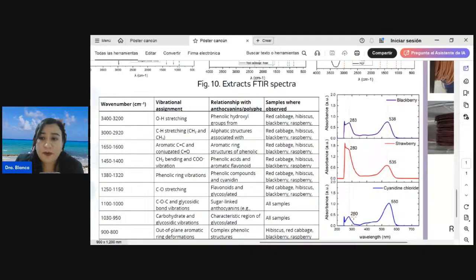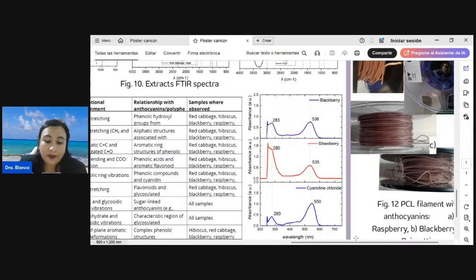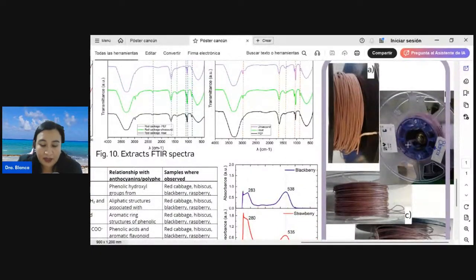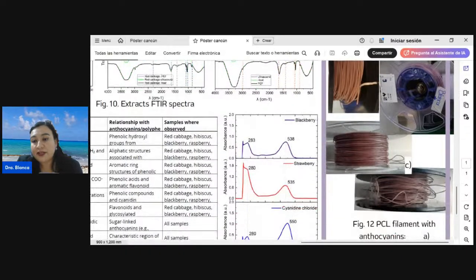Finally, UV visible spectroscopy also confirmed the presence of target compounds, with blackberry and strawberry extracts exhibiting two characteristic absorption maxima. We found 280 and 283 nanometers associated with phenolic compounds and flavonoids. And in the other, we found 535 and 538 nanometers corresponding to anthocyanin pigments. Together, these results validate the effectiveness of the extraction process and they confirm the presence of anthocyanin in extracts and also in the printed material.